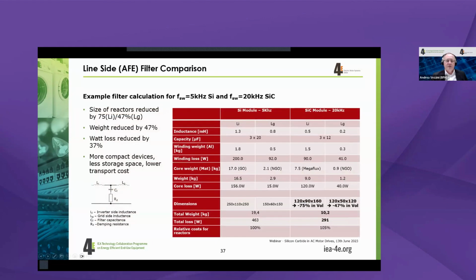The big advantage now is if you look at what happens on the filter side, going from a 5 kilohertz input switching frequency to a 20 kilohertz switching frequency means that you can reduce the size of these filter reactors here by more or less 75% for the inverter side, so the motor side, or 47% on the grid side. And that means that you have also quite a high reduction in weight from 19 to 10 kilograms, and you have also a reduction in losses.